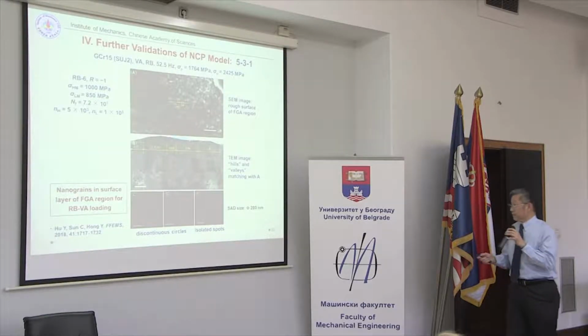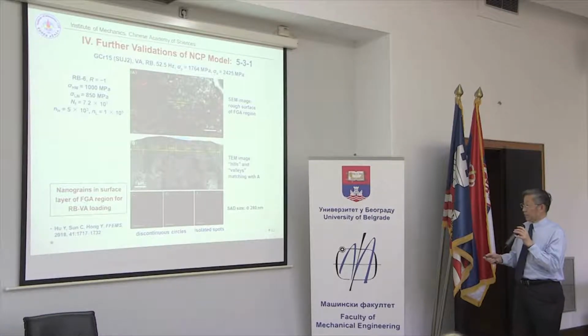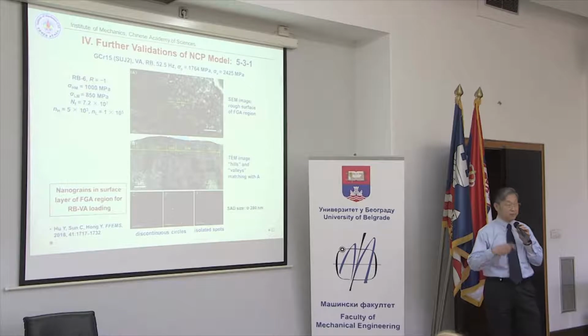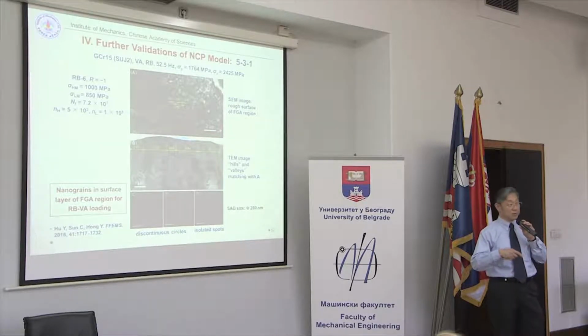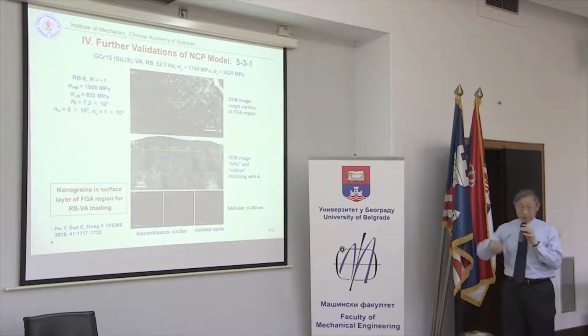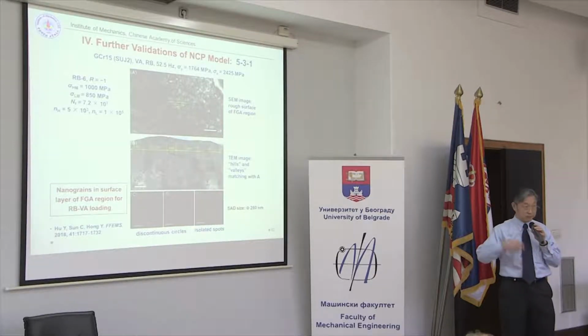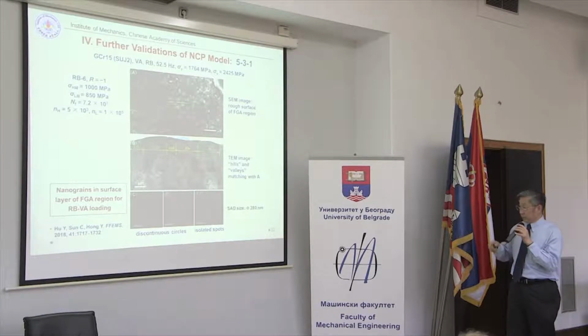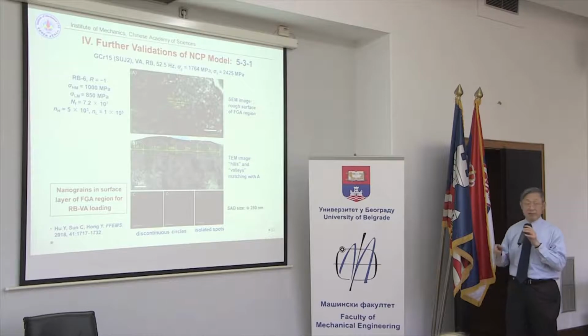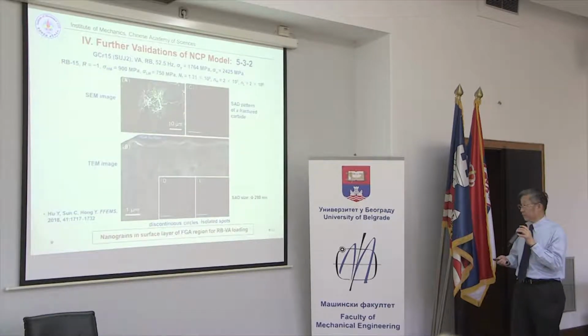And the third set of examples is again a high strength steel, but this time the experiment is used for crack growth rate during initiation, with two-step loading or variable loading. And even for this type of loading, we observe the grain refinement underneath the fracture surface. So it's also the same.